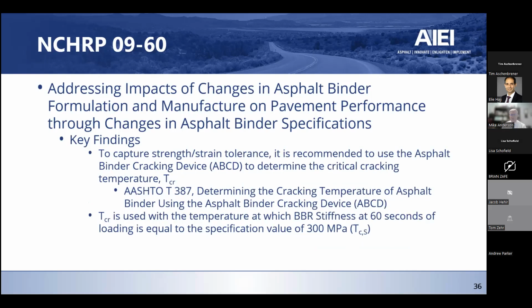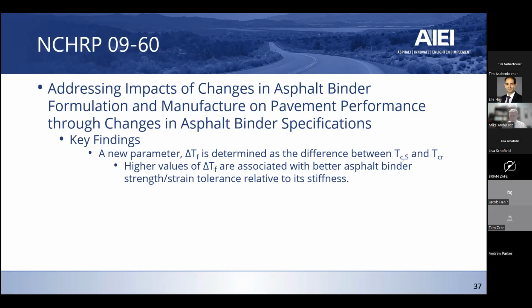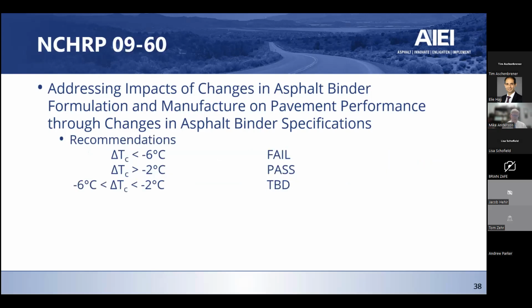What they further recommended was the use of the asphalt binder cracking device to help capture that strain tolerance of the materials. That's given in AASHTO T387. It uses the critical temperature at which the BBR stiffness at 60 seconds is equal to the specification value. We call that TCS. And then it uses the critical cracking temperature from the ABCD to create this new parameter that's called delta TF. Basically, that's just looking at the spread between what a rheological parameter tells us it ought to look like from a stress strain standpoint versus what it actually has in cracking from an actual cracking test, and what that difference in strain tolerance is. Generally speaking, if you get a broader range in delta TF, you've got more strain tolerance relative to its stiffness. So that's what that is telling us.